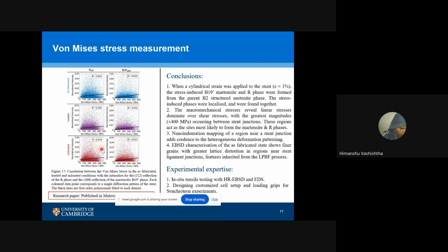When we unloaded it, again the R index goes down, meaning the fitting index is pretty poor. So we cannot quantify it properly because the fit index is not that good. But when you compare the as-fabricated and unloaded states, you can claim that during the loading condition, these phases are forming, which we have captured during the XRD maps I showed.